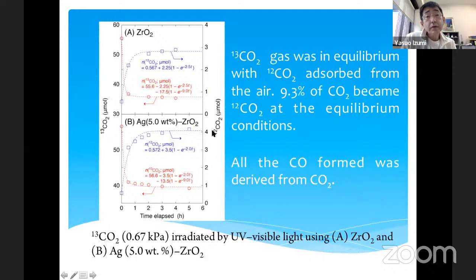both for zirconia and silver zirconia cases. And the content of the 12CO2 was about 3 among 55. So 9.3% of the CO2 was 12CO2, although our reagent 13CO2 contained 99% 13CO2. So surface-adsorbed 12CO2 was detected by this fundamental exchange reaction test.